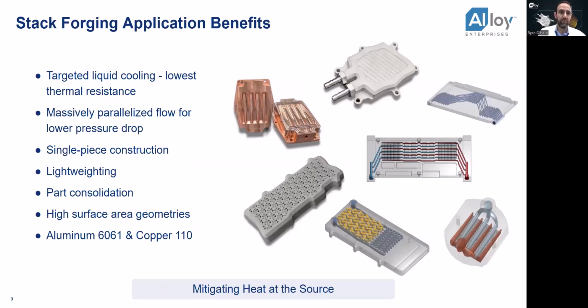So, stack forging application benefits. First, we enable targeted liquid cooling with the lowest thermal resistance. It means we're removing heat exactly where it's generated, whether it's a GPU die, radar module, or laser optic. Second, because of our ability to design massively parallelized flow paths, we achieve better thermal performance with far lower pressure drop. That reduces pumping power and frees up system energy for the mission. Third, our components are made in single one-piece monolithic construction. Again, no brazing, no gaskets, no O-rings.